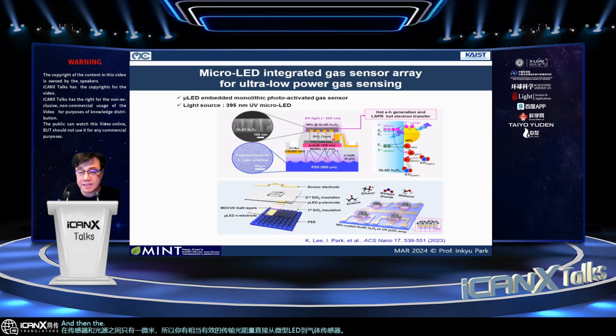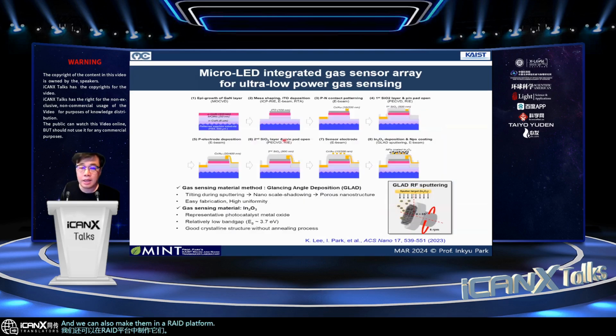And then the advantage of this is actually we can lower down the power consumption dramatically. And we can also make them in an array platform. And the fabrication process is actually quite similar to conventional micro LED fabrication, but in addition, we've got some additional passivation layer with the interdigital electrode and sensor materials.